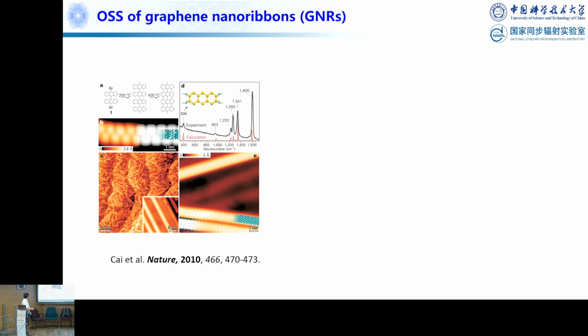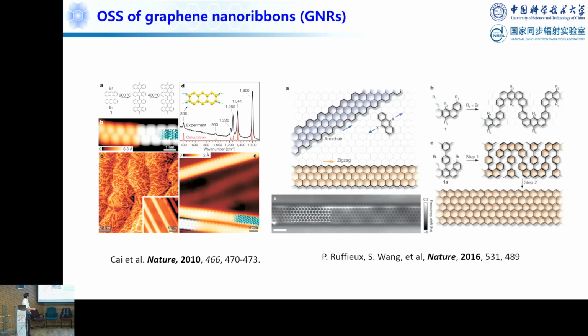Okay, so Carlos knows this much better. This is from Roman Fasel's group. They made the first graphene nanoribbons on surfaces. This paper has been cited more than 4,000 times, more or less. And then the same group also used different precursors. You can see here armchair edge graphene nanoribbons. Here is zigzag. So if you design different precursors, you will finally get different nanoribbons with different edges.